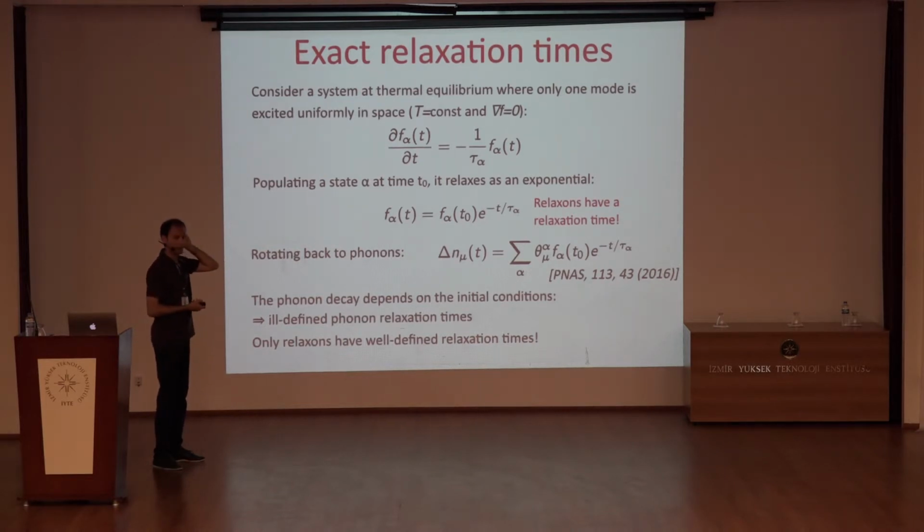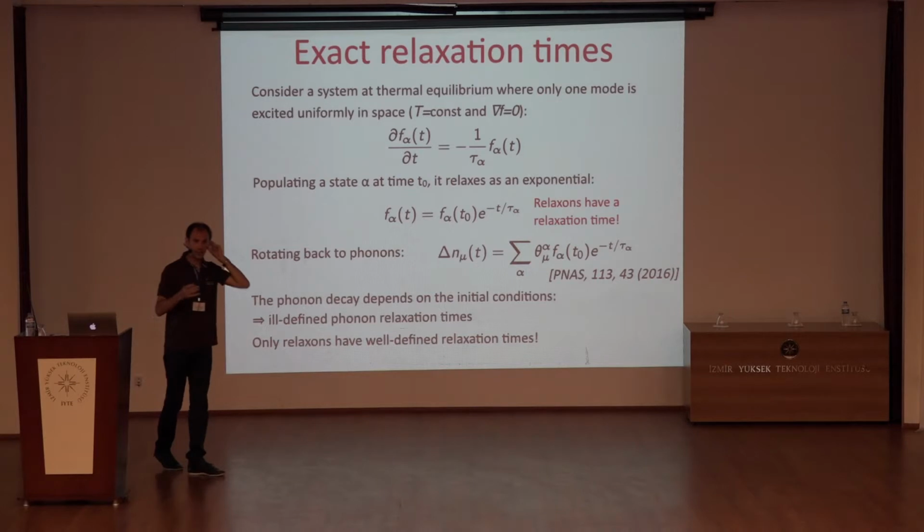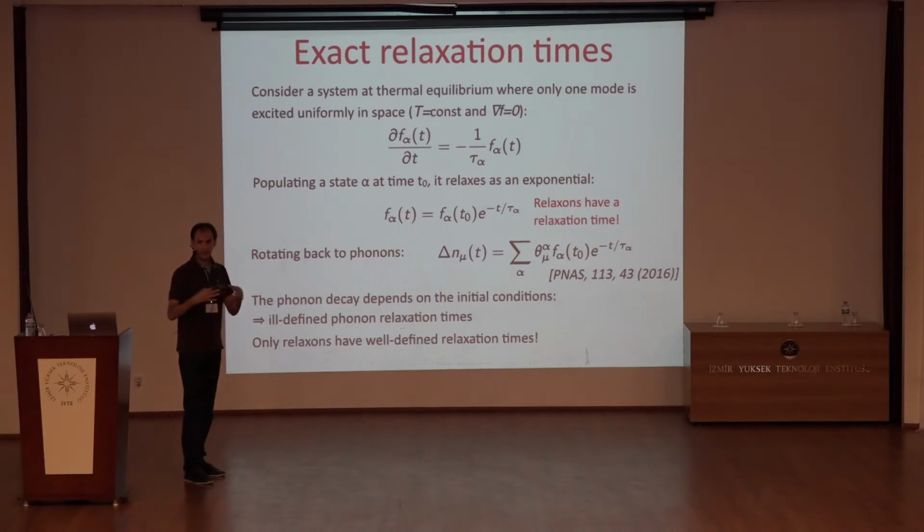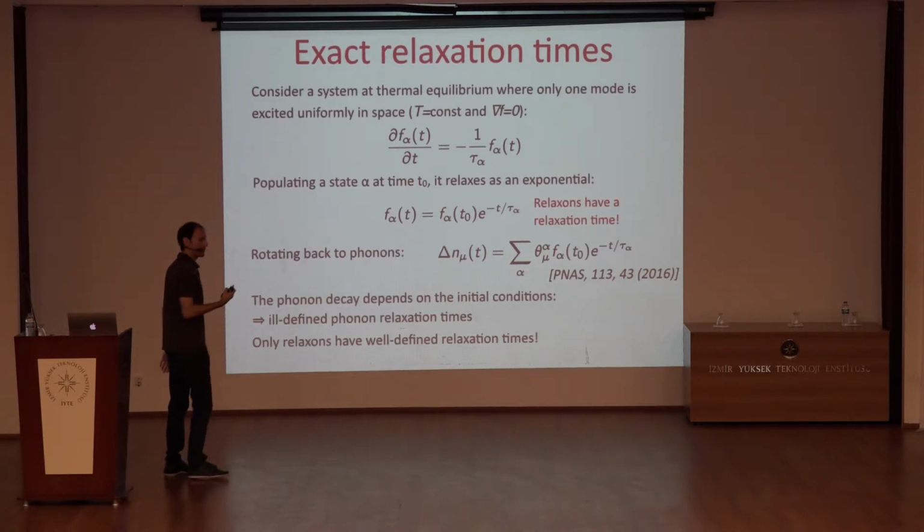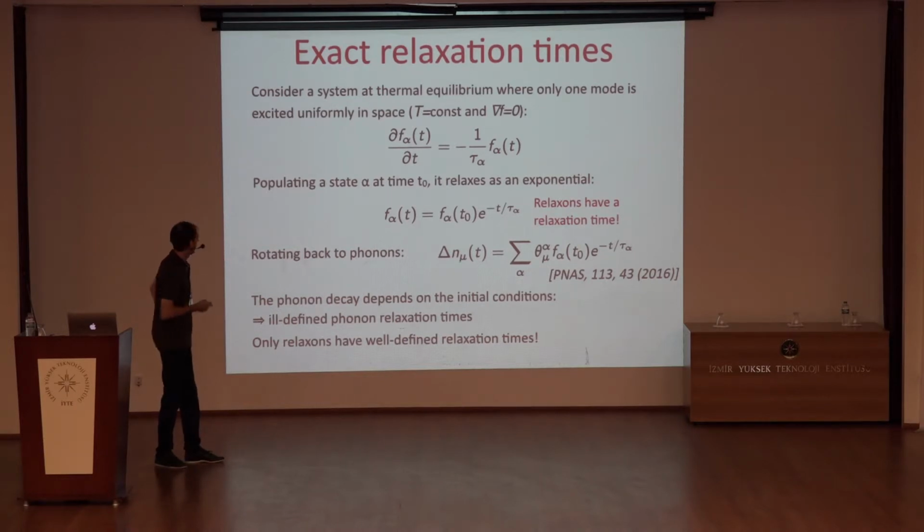Just let me also be clear that the phonon lifetime still exists and can be well defined. We have to also keep in mind the distinction between the lifetime, which is a property of the system at equilibrium, and the relaxation time, which is thermodynamical information that comes out of something like the Boltzmann transport equation, for example.